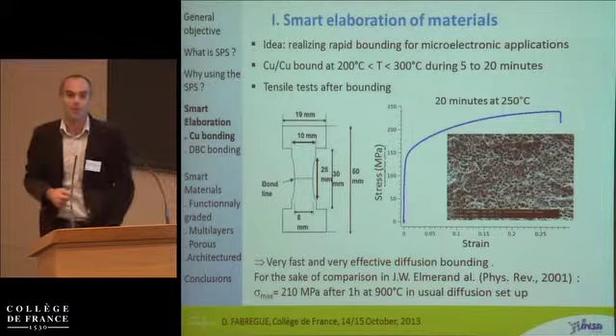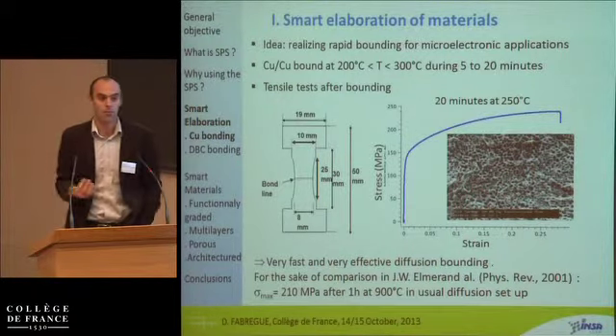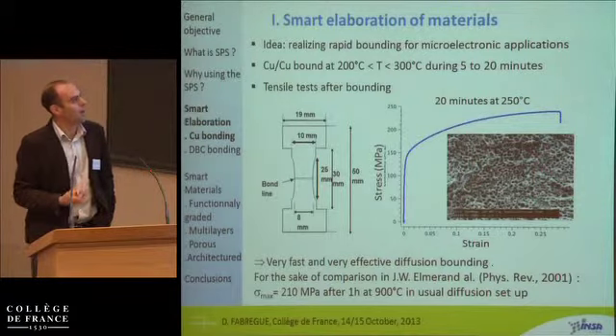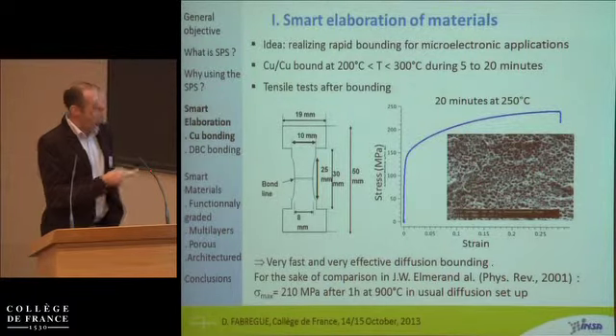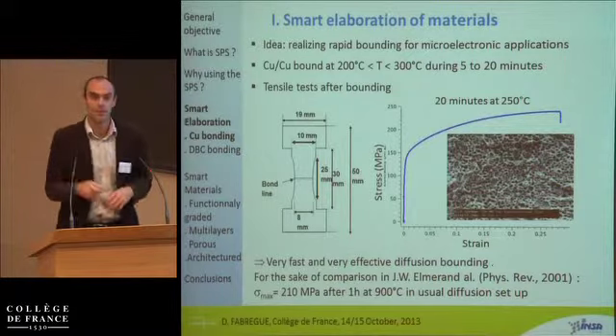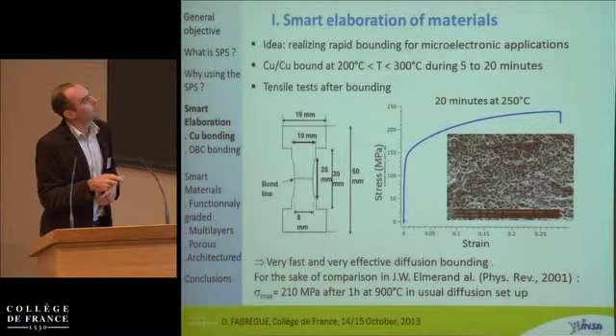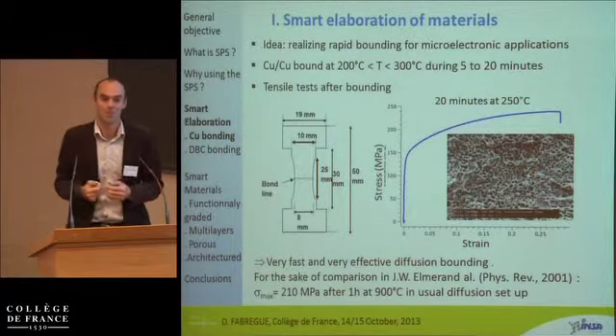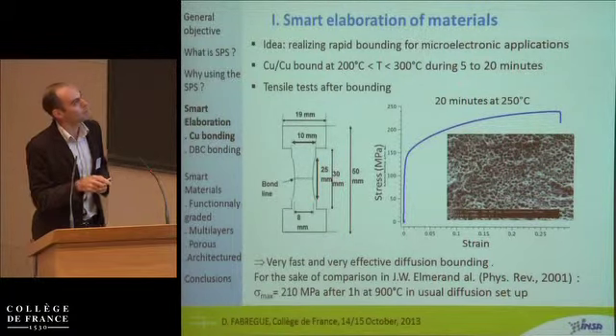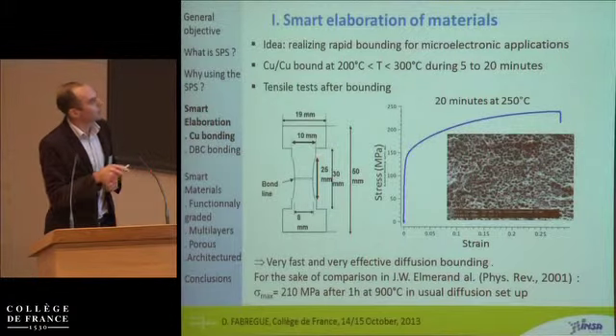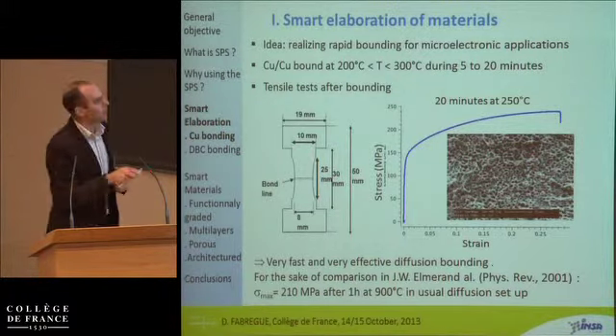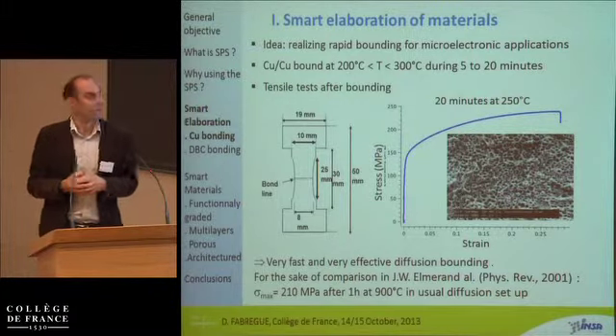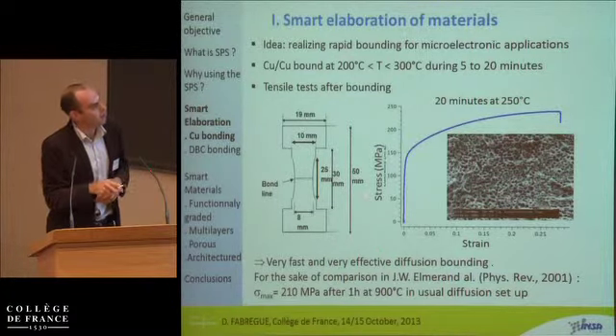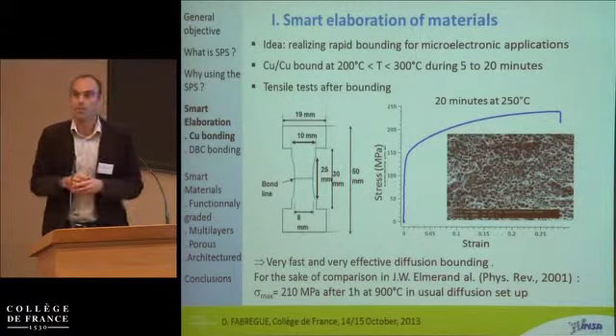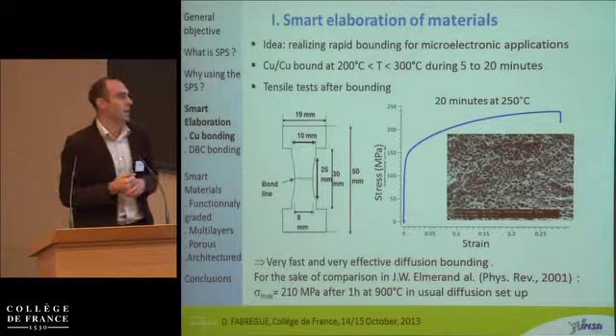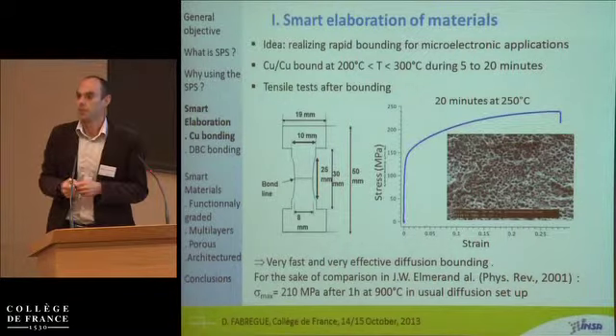So my first idea was, okay, if it enhances the diffusion, let's see if we can do something with that. So we took 2 copper parts, fully dense. We put that in the SPS at very low temperature. I will explain why I chose this low temperature, for a very short time, 5 to 20 minutes. Afterwards, you have a massive sample, which is a cylinder, and then we machine a tensile test sample in it. Then you do the tensile test, and as you can see, this is stress strain, and you have quite a high mechanical strength, about 250 MPa, and about 25% fracture strain.